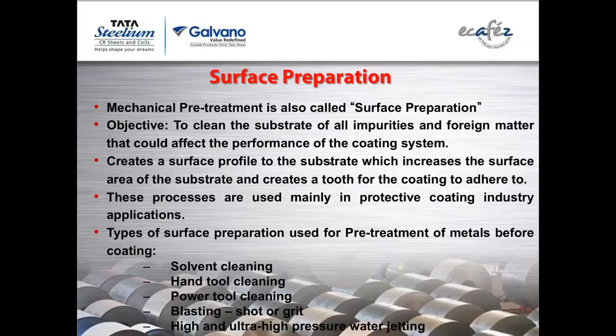If still more productivity is needed, you can go for blasting. They can be either shot or grit. We'll detail it later. And the new generation cleaning, which is called high or ultra high pressure water jetting. Normally, this is used in very few places, in very controlled conditions, because the pressures are from 15,000 psi to 25,000 psi, which is extremely high, extremely dangerous for the people who handle this equipment.